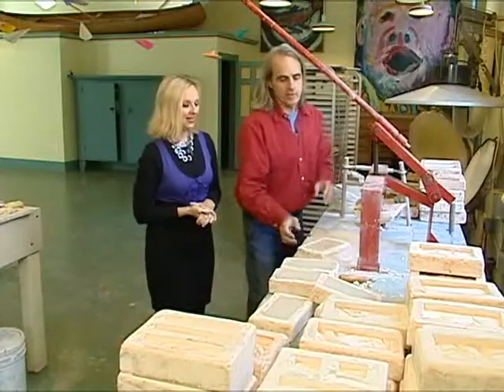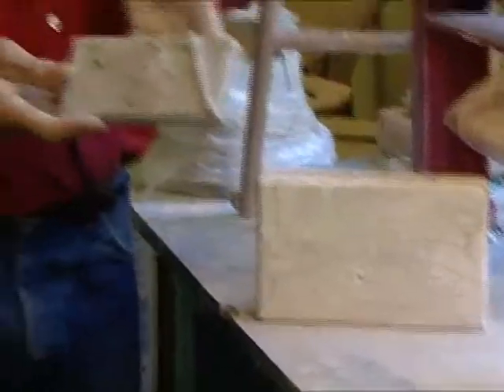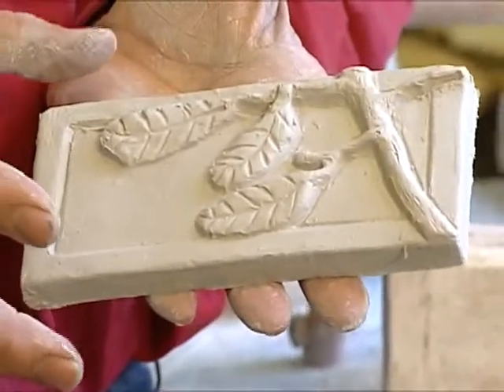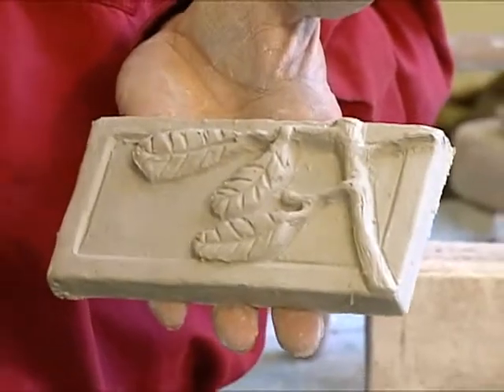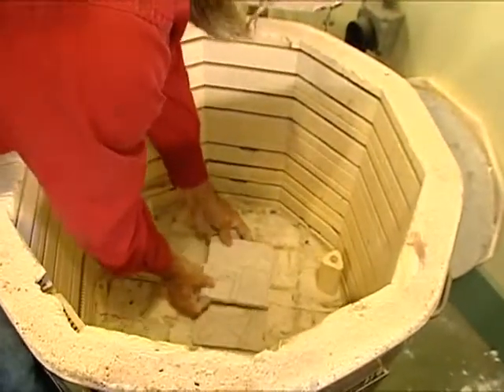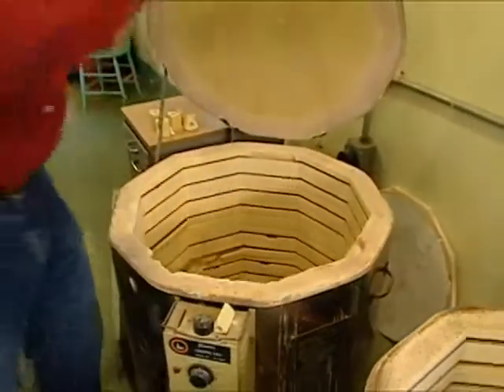Usually in about 15 minutes you can release them, so I did some a little earlier — sort of like a cooking show, you take your dish out. You pop it out, and there it is. That's part of a branch. So what has to happen next? You let them dry and air dry, usually a week or so. Then they become completely dried and they're ready for the kiln — that's called greenware. You put them in a kiln and heat them up to about 1,900 degrees Fahrenheit. That's called the bisque.